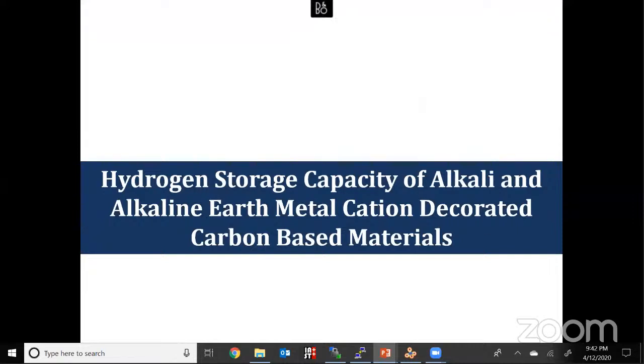And second, I calculated the hydrogen storage property of carbon-based materials, and I decorated those carbon materials with alkali and alkaline earth metal cations. In the previous work, I used anionic clusters. Here I use cationic clusters. I want to know how the anionic and the cationic clusters behave towards hydrogen adsorption. In the same way I chose boron, I chose carbon, because they are low weight materials. They won't interfere when we calculate the weight percentage, since they have low molecular weight and won't affect the weight percentage of the system.